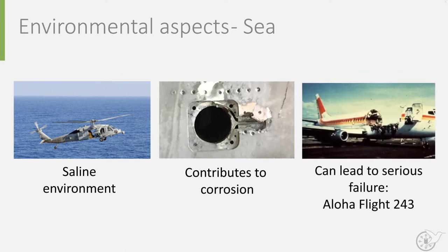As was the case for the ill-fated Aloha Airlines flight 243, that lost part of its upper fuselage during flight. The cause was determined to be a combination of fatigue due to the many short distance flights, in combination with crevice corrosion caused by the aircraft operating in a coastal environment.